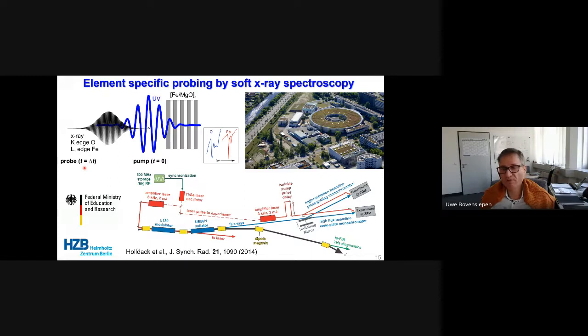So this experiment we performed at the BESSY synchrotron, where a couple of years ago, together with colleagues, we could set up, due to funding of our Federal Ministry of Education and Research, a pretty sophisticated pump probe experiment, exploiting the femtosecond laser-induced acceleration of the electrons in the storage ring. So this is the storage ring. Here we have this interaction of the electrons in the storage ring with this amplified laser. Then there's a bending magnet to separate the accelerated and the non-accelerated electrons. And then we have here a radiator which emits the femtosecond X-rays, and all the way down here to experimental stations where we have then also a laser for pumping these samples.